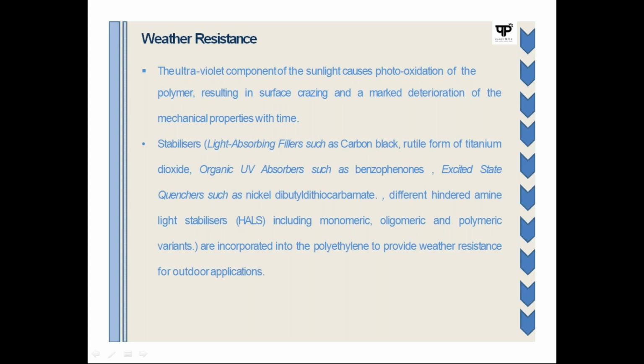Now what I mean to say is that the cost of this UV stabilizer which is non-black is much higher compared to carbon black, which is less costly. But in this case, in both cases, whether we use carbon black, a non-black, or a black one, dispersion of these additives is very important.